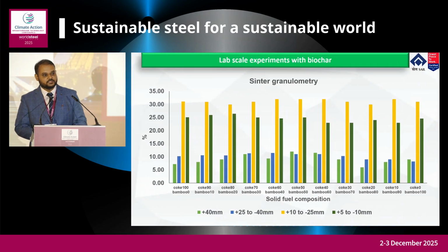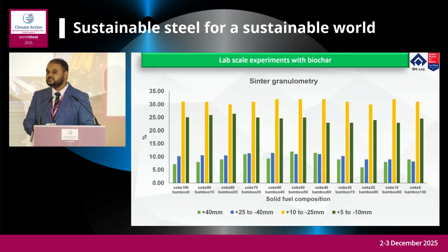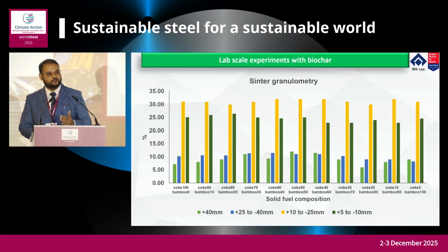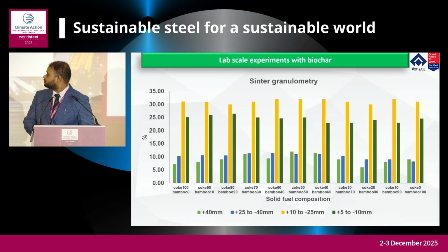Next is the granulometry stage. This comes directly from the mean size figure. Our requirement is 5 to 40 millimeters typically for the blast furnace, and we have done a good comparison of coke versus biochar, because ultimately we have the mandate to replace coke breeze, not fully, but up to whatever percentage we could. Again, our standard ratio at lab scale was around 20 to 30%. With these data, we have moved to our plant to validate this lab scale data at industrial scale and to see what benefits we can achieve.